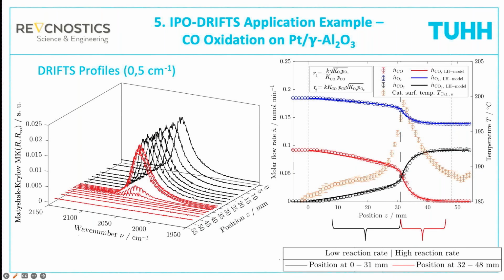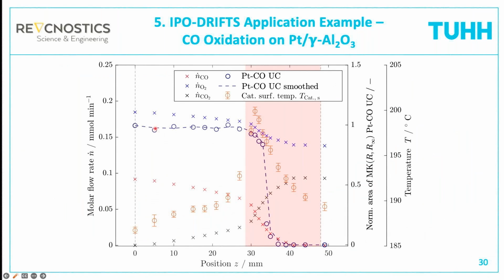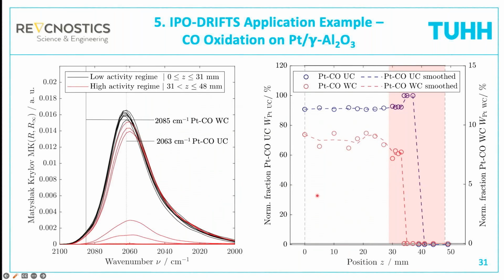But in general, this works very well. Now you can put this all together and plot the species profiles in the gas phase, the temperature profile, and the adsorbed CO. You see the constant reaction rate while the surface is basically occupied with CO, and then the reaction picks up speed because the CO is desorbing and we have more sites available for the reaction. And now you can even work out some more fine details.